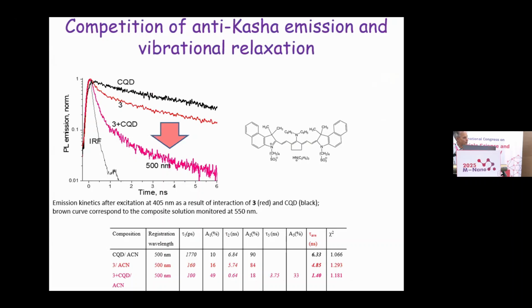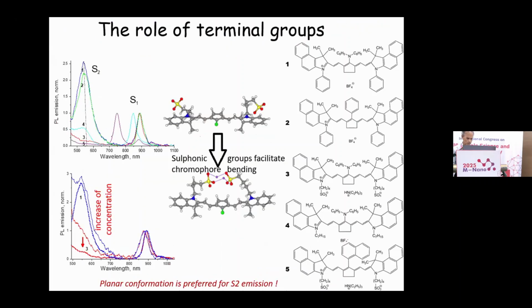For the other dye, we observed similar processes, when the relaxation in the presence of carbon nanoparticles decreases very significantly, resulting in a change of the time constant of the emission. The other mechanism which helps to realize anti-Kasha emission is the backbone conformation of the molecule. Depending on the terminal groups which the molecule possesses, these terminal groups help the molecule to twist in solution or on the surface of some surfaces.